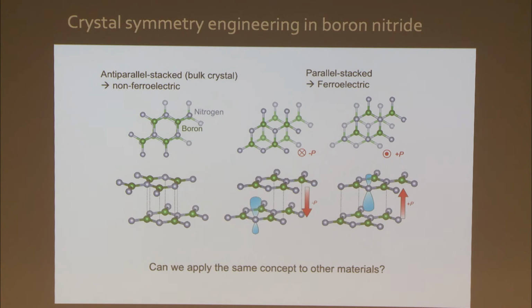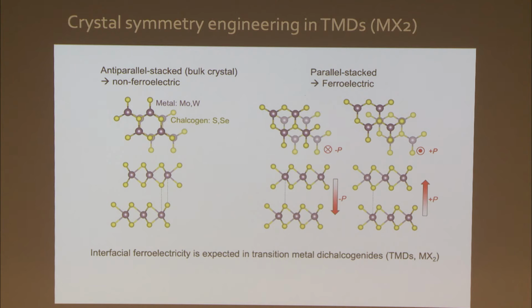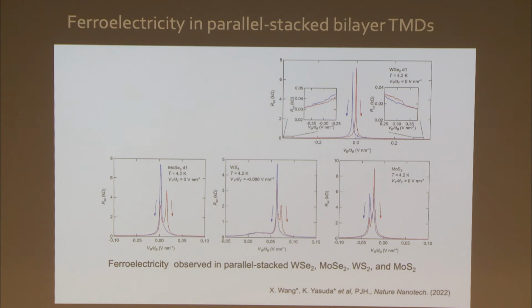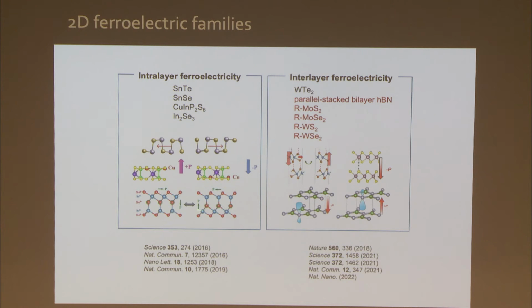Now, this exact same trick, we have hundreds of materials. We have this bipartite lattice, okay? So the same crystal symmetry engineering trick that we did with boron nitride to obtain ferroelectricity, we can do it with many other materials. And in particular, with the transition metal dichalcogenides, which are semiconductors, okay? They also can get stacked in AB and BA type of stacking, which has opposite electric dipole moments. And in fact, we have realized ferroelectricity using the four most common transition metal dichalcogenides, WSe2, MoSe2, WS2, MoS2. These work at room temperature. They're all robust, and they are all ferroelectric. Okay? So within a matter of maybe a year and a half, we have essentially doubled the number of two-dimensional ferroelectric materials, but this list can actually be much, much longer because we have many materials with bipartite lattices.